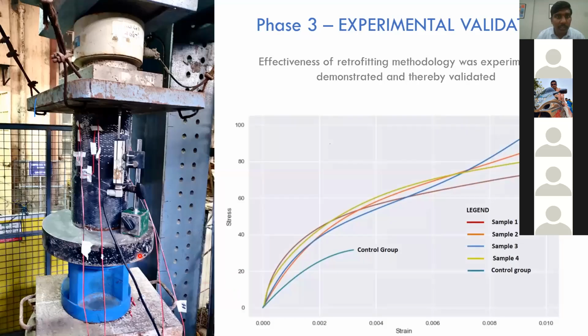And again, we needed an experimental validation to show the clients, the owner of the bridge, that the FRP wrapping will provide sufficient strength. So this is how the test setup was done. They wanted to correlate the increase in compressive strength due to FRP wrapping, to select which kind of FRP, which company's FRP they wanted. This test was done in one of the labs of a reputed college in Bombay. An RCC cylinder of the same grade as the pier was cast. After 28 days, FRP wrapping was performed. Strain gauges were connected to it, and then an LVDT. And we tested several different samples like this in the same configuration, and also without FRP.